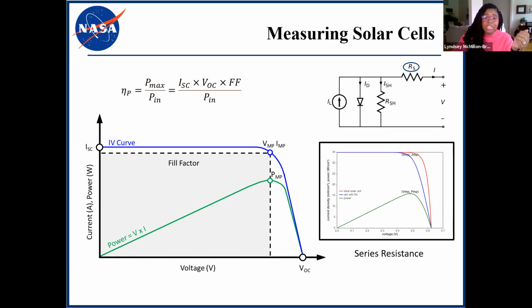Your series resistance would look something like this, and that mainly reduces your fill factor. So series resistance is generally caused by internal resistance between the absorber and the contacts, or resistance of the contact itself.